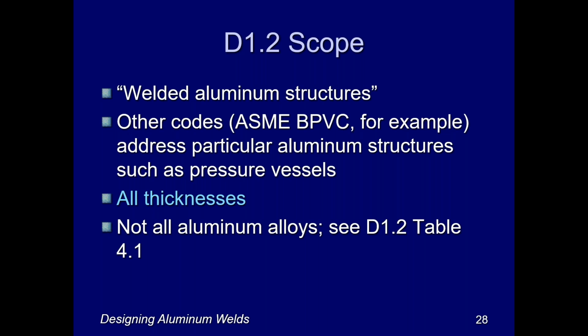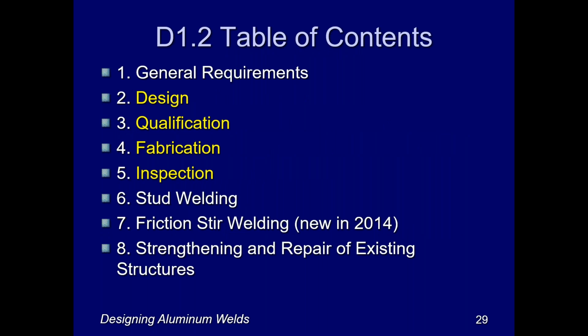It covers all thicknesses of aluminum parts. So you can weld together sheet metal, you can weld together 8-inch thick parts. But it does not include all aluminum alloys, rather only those that it lists in a table 4.1. And so it typically does not include aerospace alloys like the 2000 and 7000 series because of their copper content, they're not easily arc welded. They can be friction stir welded. That's another reason to be aware of friction stir welding. But those are the only limitations in D1.2.